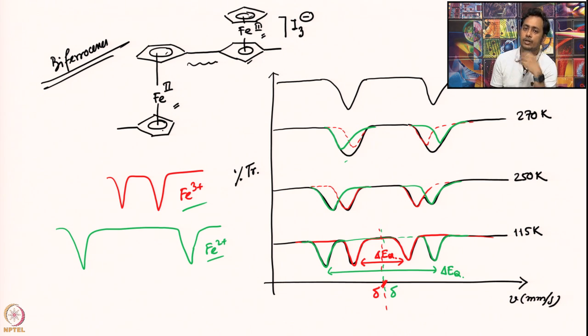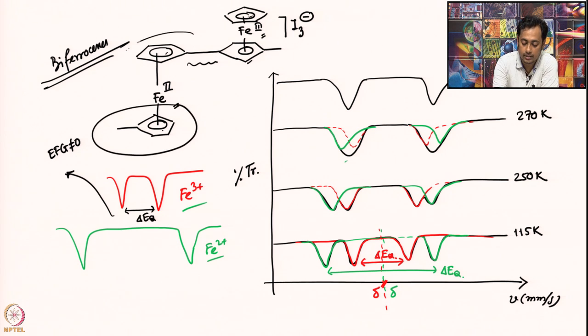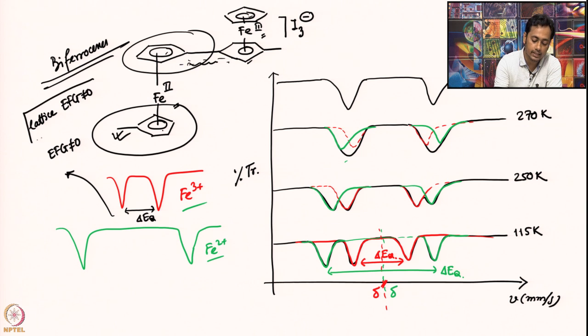But previously when we discussed, we said that the ferrocenium has an electric field gradient almost close to 0, and that is why it has a delta EQ value close to 0. But over here, it has a very good EFG value, and that is why we have this delta EQ. That is because now I have an electric field gradient that is non-zero and quite significant. Why is it so? Look into the ferrocenyl system. One has only a methyl group, one is connected to a biferrocene system, and that is bringing some lattice electric field gradient which is non-zero in nature, making the gradient significant. But this is still saying it is an iron plus 3 system.